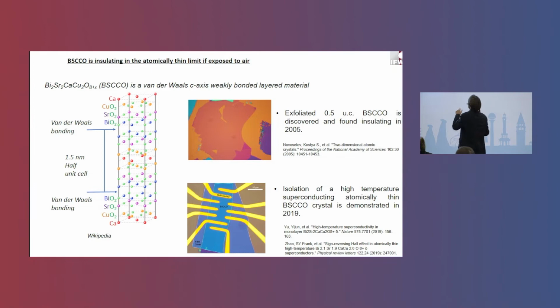Now BSCCO generally, as shown by Novoselov and others, can be stamped with Scotch tape onto a substrate in the thin limit, as a two-dimensional atomic crystal, by breaking the bismuth oxide bonds. The problem is that when you do that, the oxygen basically boils out of the system, and the system becomes insulating. More recently, we have done some work in two different groups, and shown that you can isolate the high-temperature superconducting, atomically thin BSCCO down to very, very thin crystals. This shows that you can retain the maximum critical temperature of 90 Kelvin for bismuth 2212 down to the very thin limit.